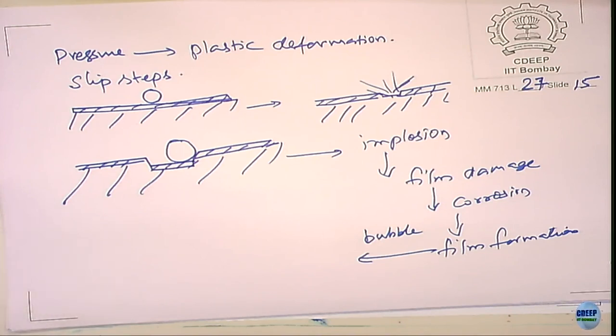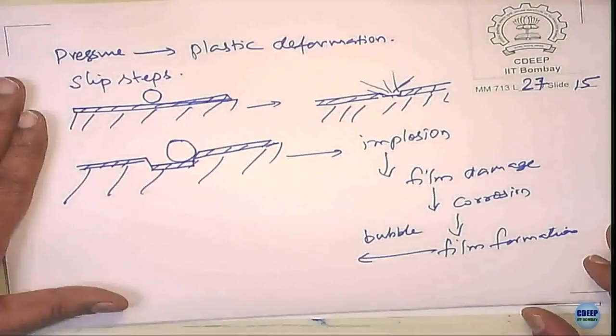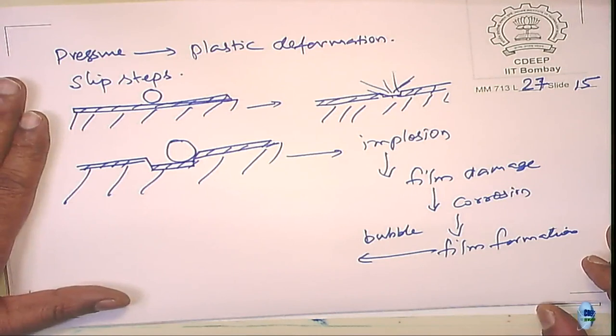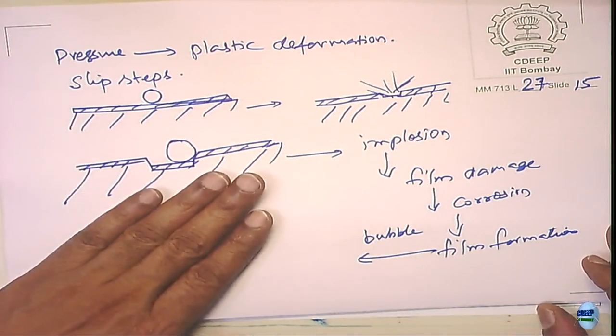So the pit grows primarily because the surface becomes rougher. It becomes easier for the bubble to sit on the surface. Please notice that the implosion by itself is not a problem. If it happens within the liquid, I have no problem. It happens only on the surface, it causes the damage. So, the cavitation damage that is occurring here is more of a mechanical damage.